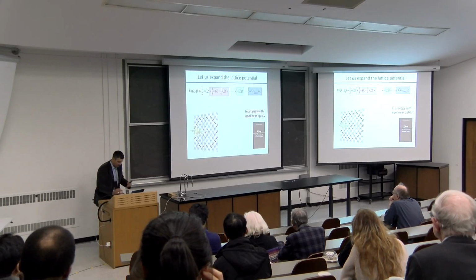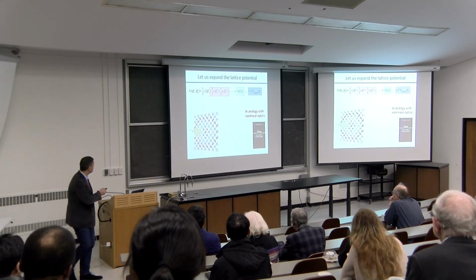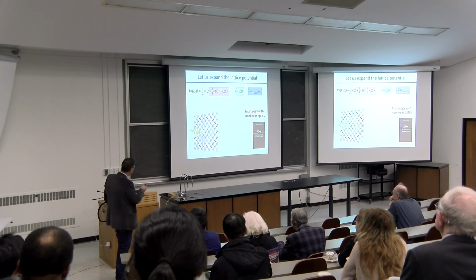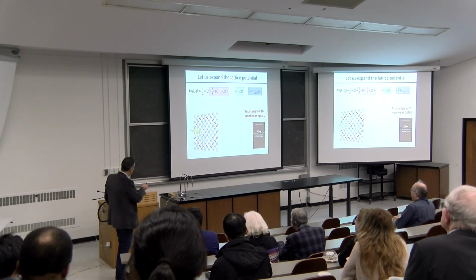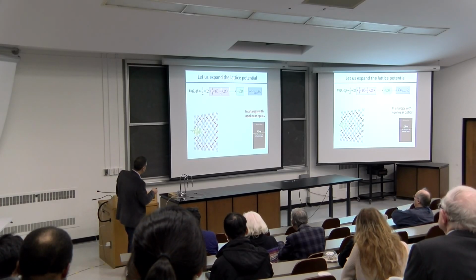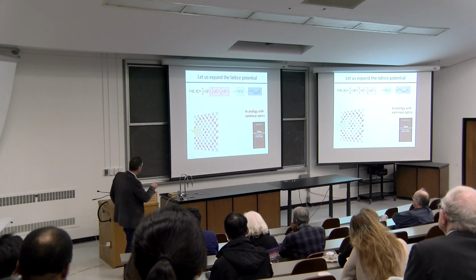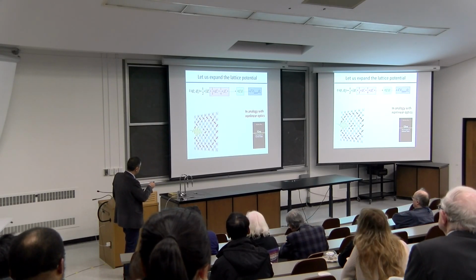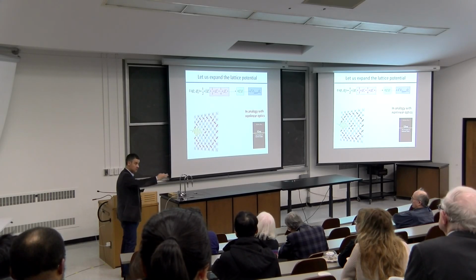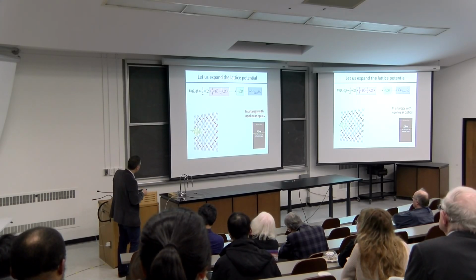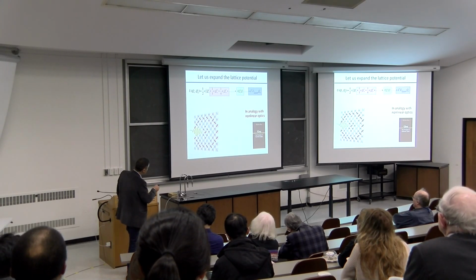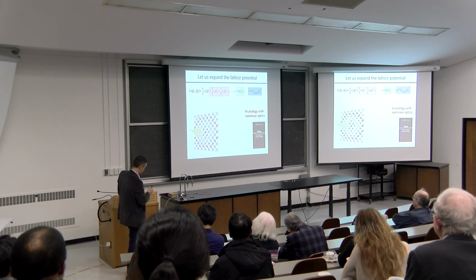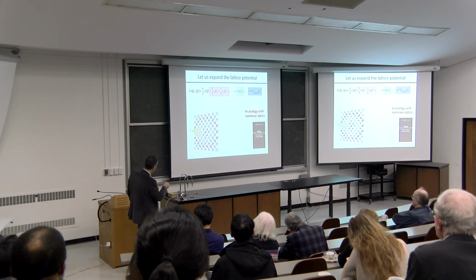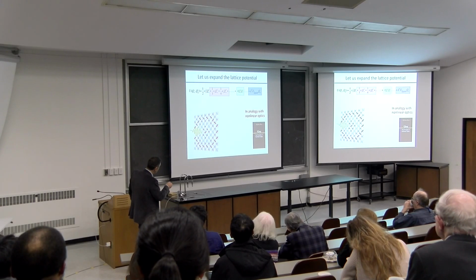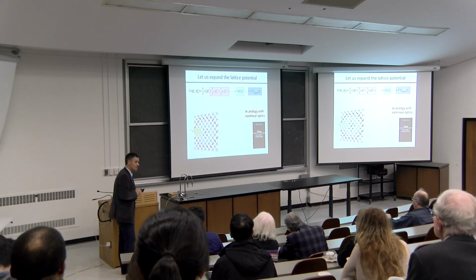And as we do in nonlinear optics, we can start expanding this energy. As before, the linear response was an energy that only depended on the normal mode, Q_IR, which is the mode that I'm resonant with, and on the laser. Now, I can expand the lattice potential, and one of the things that I can do is consider all the terms of the mode that is being driven, third, fourth, and fifth order. And then there's going to be couplings between different normal modes. I'm imagining that this system respects inversion. If the system respects inversion, then I won't have any odd modes here, and there will be couplings in which the driven mode will only come in to even powers.